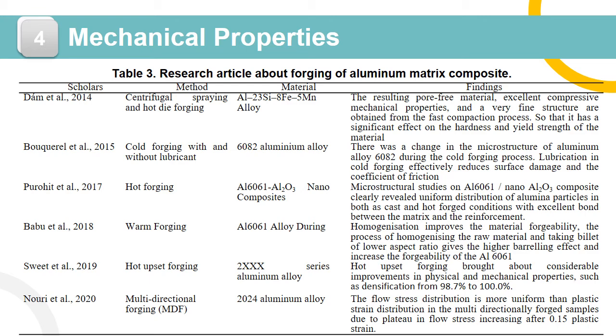hot forged condition. Babu et al. 2018: it was found homogenization improved the material forgeability. Sweet et al. 2019: it was found hot upset forging brought about considerable improvement in physical and mechanical properties. Nouri et al. 2020: it was found the flow stress distribution is more uniform than plastic strain distribution in the multidirectional forge.